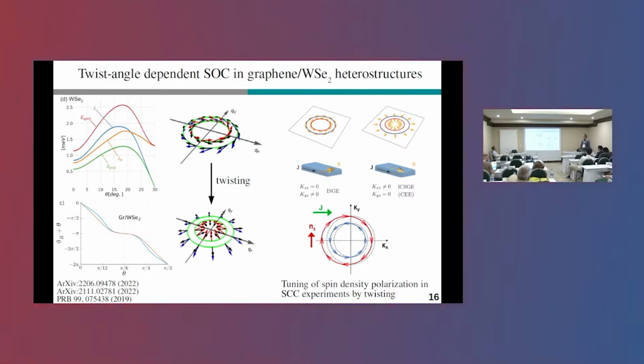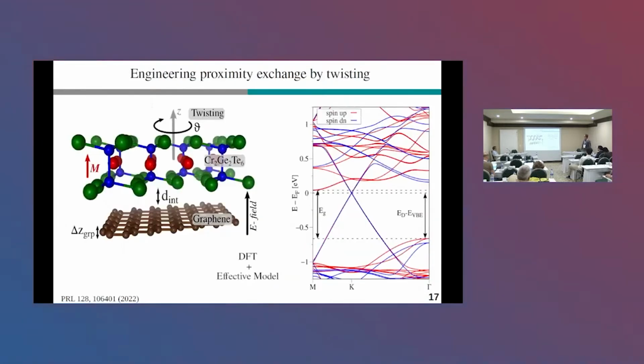And now let me switch gears and come to the actual things I would like to present, which is the engineering of proximity exchange in graphene chromium germanium telluride heterostructures by twisting. So the situation we have is like this. We fix the magnetization of the ferromagnet and simply twist. On top of that, we can apply a transverse electric field to see how things can be tuned. And what we do is DFT calculations on large supercells, and then we do the effective modeling of the low-energy states.